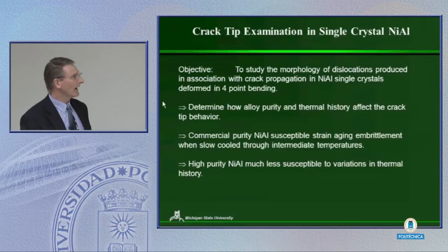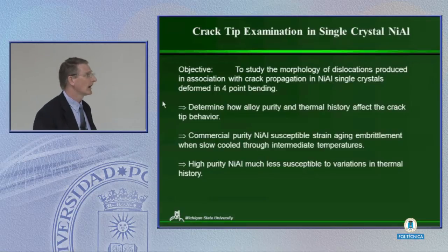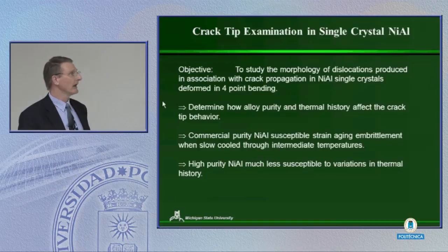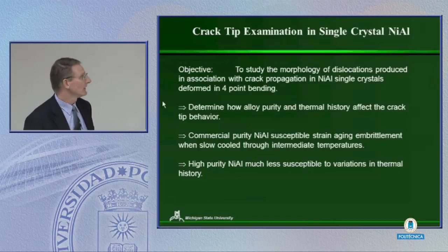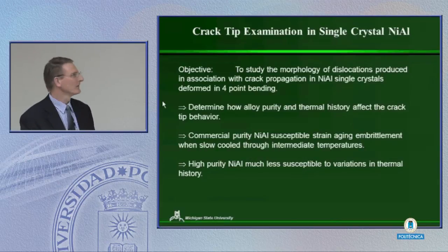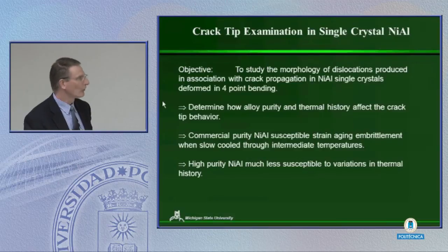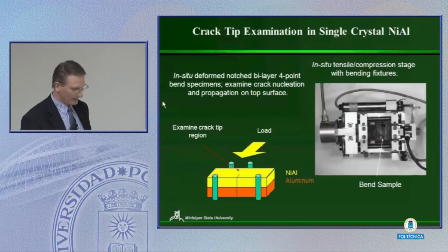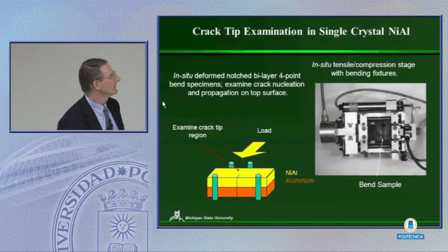We can determine how alloy purity and thermal history are affecting the crack tip behavior and the crack propagation. The reason we're looking at this is commercial purity nickel aluminum is susceptible to strain aging and embrittlement. It becomes essentially a zero fracture toughness material if it is cooled the wrong way. High purity nickel aluminum is much less susceptible to these variations in thermal history.